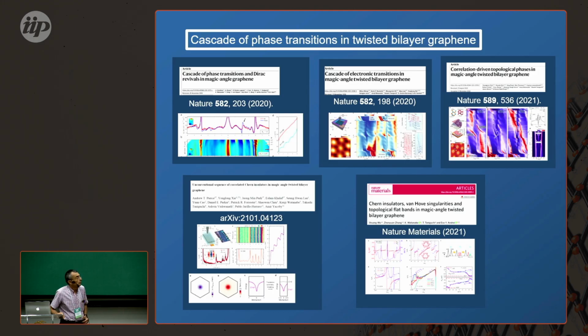These features have already been observed in many experiments. They are the reason for the so-called cascade, and a number of STM experiments, compressibility experiments and so on have confirmed that the flat bands are only flat, or maybe flat at charge neutrality, but definitely they have a width on the order of at least 20-30 meV